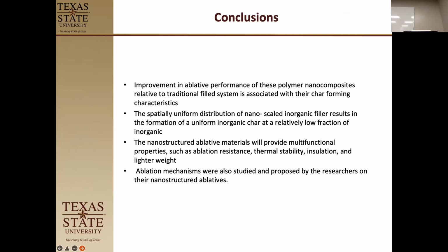So basically, having those nanomaterials in there, specifically the alumina, it gave it so the top was alumina particles, and that actually had a positive effect on the char making. They uniformly filled the materials with the nano-alumina specifically, and the uniform inorganic char at a relatively low fraction. So what they're saying here is that only 5 weight %. They got it well dispersed, but that was what ended up on the surface when they looked at the collections.